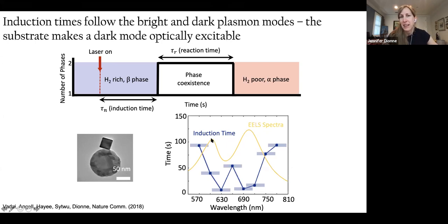And I think this is pretty exciting because the catalysis community has focused for many, many decades on how the substrate can influence activity. That substrate not only influences, say, the strain that a particle might feel when it's sitting on the sample, but it also changes the local density of electronic states and the local density of optical states, such that you can wind up getting some of these plasmonic modes to be optically excitable just based on the substrate.